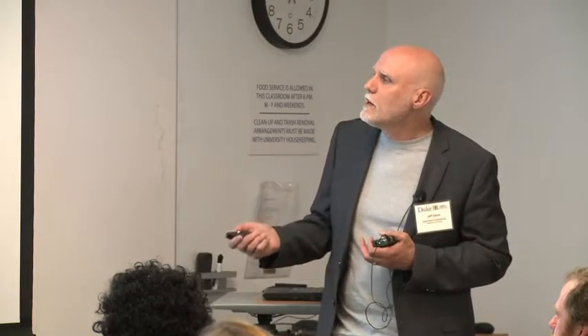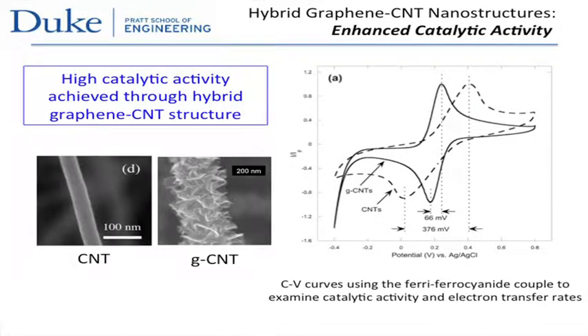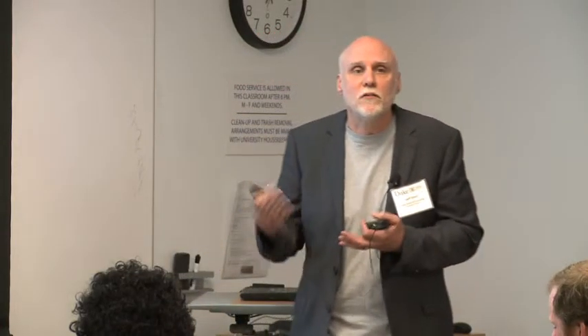And we also find the same thing with the catalysis. This is shown here, where we're looking at just a ferrocyanide couple, and we see that the carbon nanotubes have a very strong separation between the redox couple. And when we put on the graphene foliates, that redox couple comes closer together, so more reversible, faster reactions. So that can be for any kind of catalysis, and it's been shown for a couple different types in our lab.